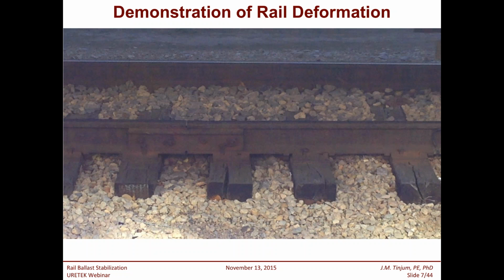There are 2 issues with that cyclic displacement. Number one, that dynamic displacement caused premature aging or fouling of that ballast substructure. As the ballast particles, say 2-3 inches in diameter, rub against each other, the edges start to break off, and as those edges break off, the track becomes a little more fine-grained, and that extra fine-grained material retains moisture. For those of you that are civil and geotechnical engineers in the audience, moisture retention is quite bad for the structural capabilities of the system, and the strength of the system goes down with that increased moisture retention.